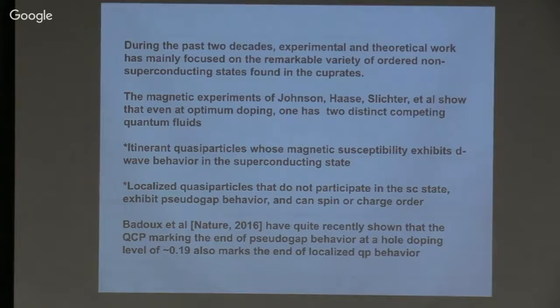And the sort of final proof in all of that was that there's a quantum critical point you can identify in transport measurements. This is work by Badoux et al. with Louis Taillefer in Canada. And it shows that it's exactly the same point at which you get rid of the pseudogap, you also get rid of localized behavior. So around 0.19, you have a second quantum critical point. It's the metal-insulator transition for the local moments. You get rid of all the local moments, and you're just left, to the right of that, with itinerant electrons that can superconduct.